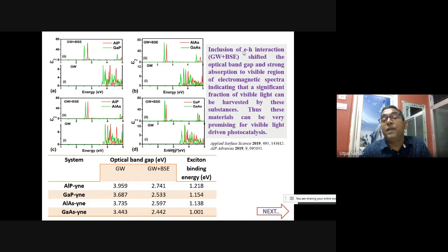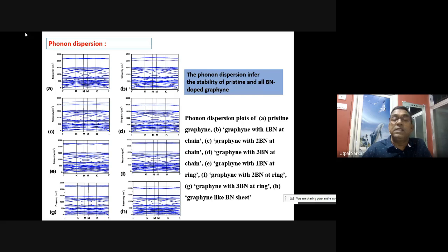So inclusion of electron-hole interactions shifted the optical band gap and strong absorption peak, as you see here, to the visible region of the electromagnetic spectra, indicating that a significant fraction of visible light can be harvested by this substance. Thus, these materials can be very promising for visible light driven photocatalysis. Now, this is the phonon dispersion curve, which shows that all these systems are dynamically stable.